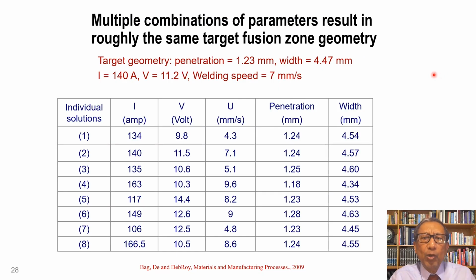Each of these solutions give us the fusion zone geometry we want, which is written here. Penetration 1.23 millimeter and width would be 4.47 millimeter. And in each case, for different values of current, voltage, and scanning speed, we get more or less the same depth of penetration and same width.